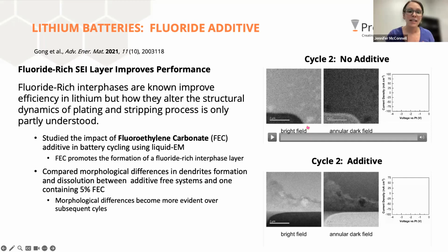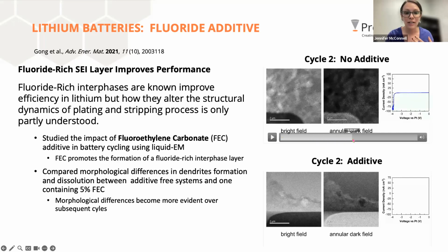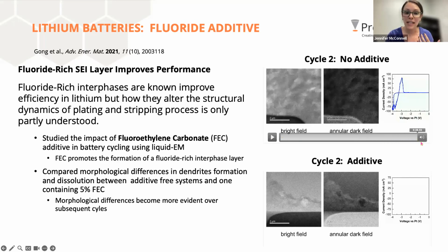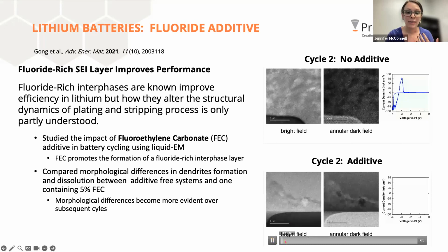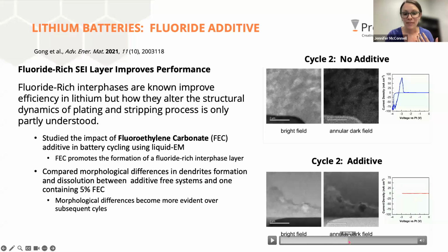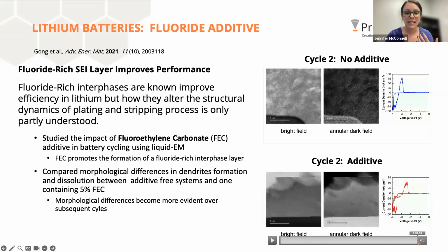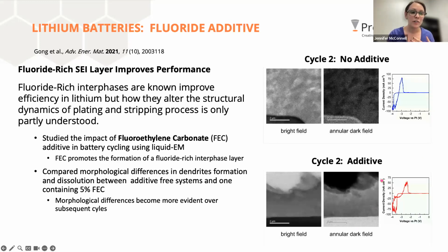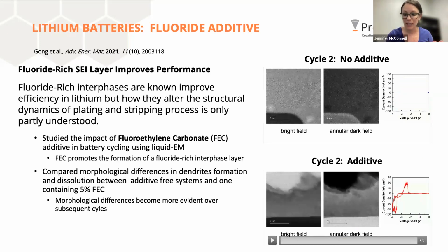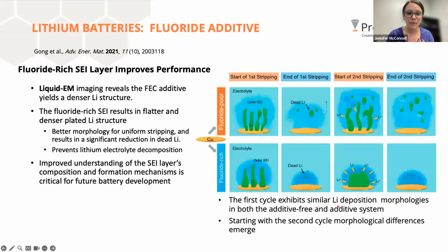Why is that? They've got a couple of videos here that I have to say aren't my favorite. I'm going to speed them up because they're a little slow, but they're doing a charge-discharge cycle here. And you see the lithium dendrite growth. This is without the additive, the fluorine additive. And then down here, they do a cycle with the additive. Like I said, the videos are a little hard to see. You also have gas bubble formation right up here, which is quite common during electrochemistry experiments in the TEM.